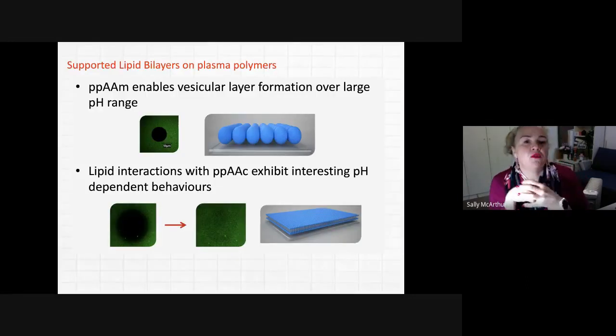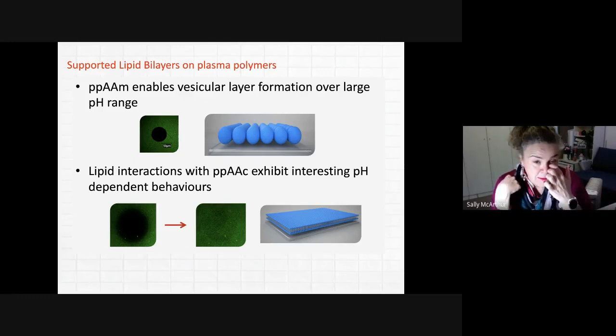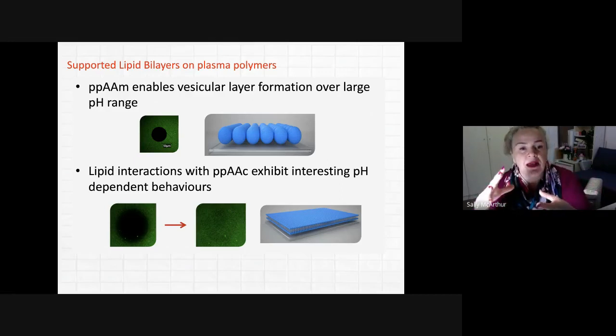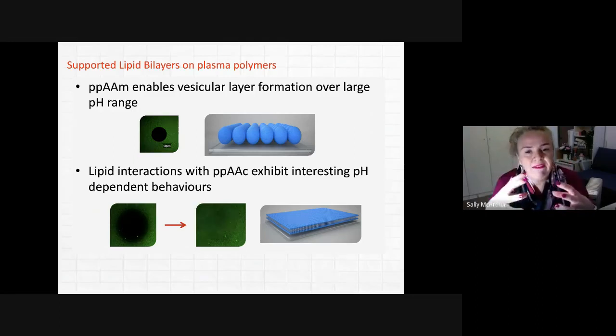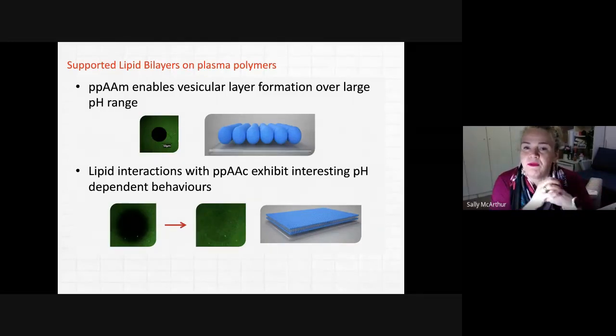And what we found was that if we took an allylamine surface, we couldn't drive that change. So allylamine has an isoelectric point of around pH 9. If we introduce vesicles below that, the surface is neutral or maybe even negatively charged, but above it, it becomes positively charged. But what we found was that the vesicles just stayed intact no matter what pH was on the surface, and they packed down really densely. And they weren't able to be rinsed off by any pH change either.